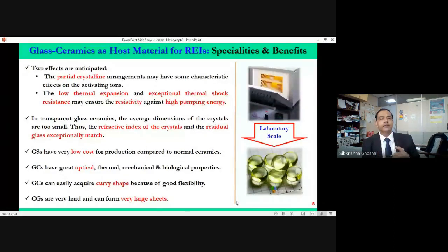Another reason why we use these glass ceramics, the benefits come from another reason. They are partially crystalline, so the crystallinity plays a role. Remember one thing, the rare earth will not show any effect by itself. It chooses a particular host and it shows different effects. Why is the host important? Because depending on the symmetry and asymmetry of the local environment, the local structure of the host, of the crystal or the ceramic or the glass, the effect of the rare earth would be entirely different.